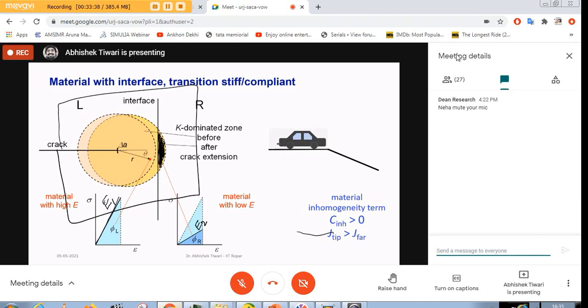That means for the same amount of energy I am supplying, the crack tip is feeling more energy. So J tip is greater than what we are giving. We are not creating anything, but because of this interface this is happening. This is similar to driving the same car without changing any parameter, but then I hit a downhill road and the velocity of the car will increase without changing anything. This is an idea which can be used to change the crack drive. So we can ask the crack to move according to our will if we can specifically use this material transition.